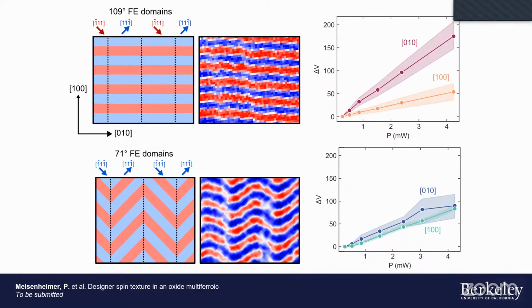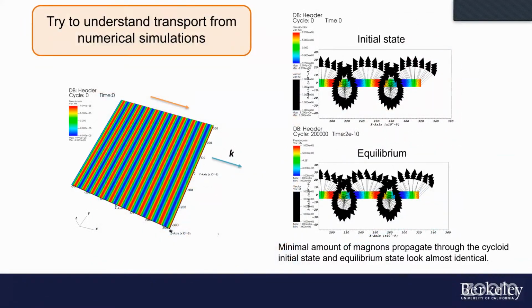Additionally, and I think this is a cool observation if it's true, but we're not totally confident that it's true, if we pump spin this way, it's hard, we get a low value. If we push magnons to the right and the left, it's easy and we get a high value. If we push magnons along the 45 degrees, we would expect something that looks like √2 between hard and easy, and that's about the value that we see. So I think if that's true, that's pretty neat. But that's not a very quantitative picture.